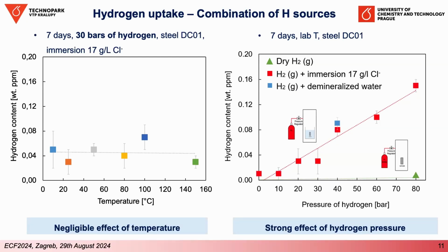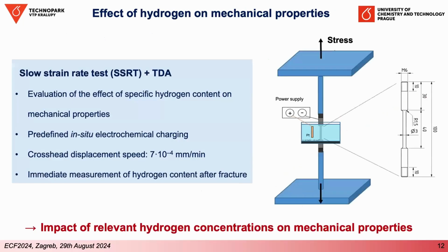We did some more sampling, and we have some results for the formation water too. Of course, because the absolute amount of hydrogen entered from the formation water is higher, even the synergy or promoting effect can reach really high absolute values of hydrogen in the steel. So what are the critical parameters? The presence of formation water, its nature, and also the possibility of MIC should be taken into account.